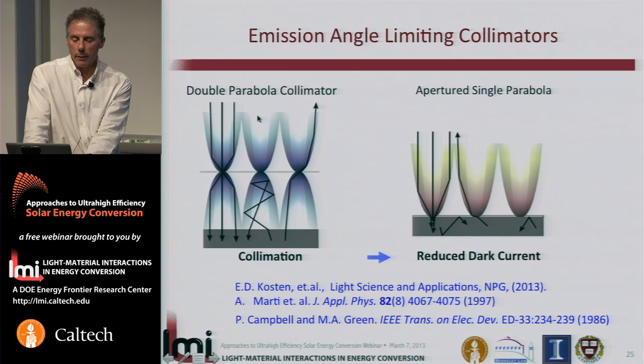And this shows schematically two kinds of structures that look like microscale versions of conventional concentrators that have the effect by photon collimation of reducing the dark current emitted from a solar cell. And because the voltage scales as the log of the photocurrent over the dark current, then it's possible by simply reducing the dark current to the minimum necessary to create the full absorption in the cell, and no more, to increase the open circuit voltage.